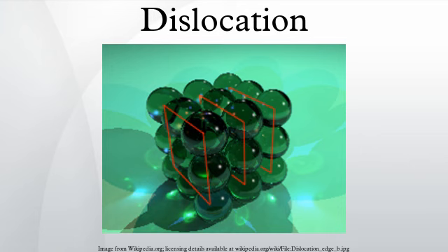Transmission electron micrographs of dislocations typically utilize magnifications of 50,000 to 300,000 times. Some microscopes also permit the in-situ heating and/or deformation of samples, thereby permitting the direct observation of dislocation movement and their interactions. Note the characteristic wiggly contrast of the dislocation lines as they pass through the thickness of the material. Note also that a dislocation cannot end within a crystal. The dislocation lines in these images end at the sample surface. A dislocation can only be contained within a crystal as a complete loop.